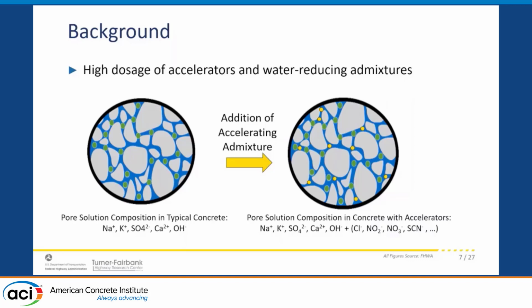So I've highlighted here the presence of chlorides in case we're using chloride-based accelerators, nitrates, nitrites, and so on. So it was not trivial to just assume that it would be okay to test these mixtures with electrical tests, because once we start affecting the pore solution, we're going to ultimately affect also the bulk electrical properties.